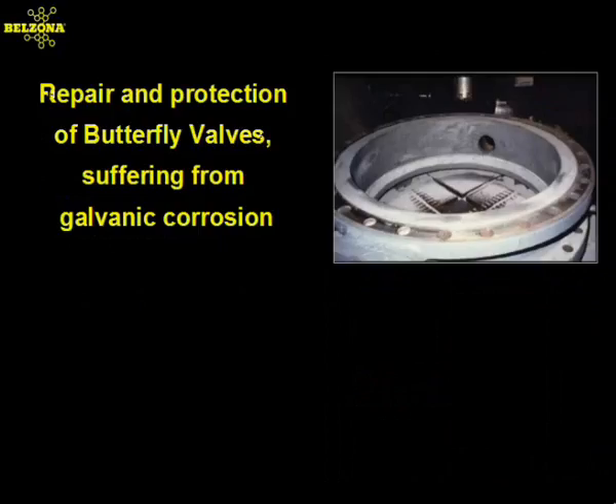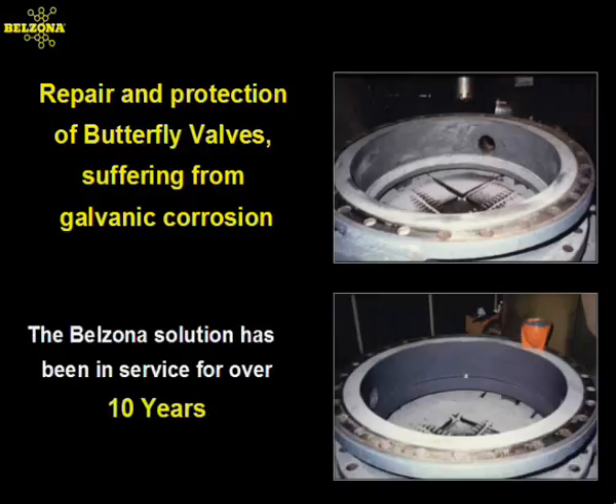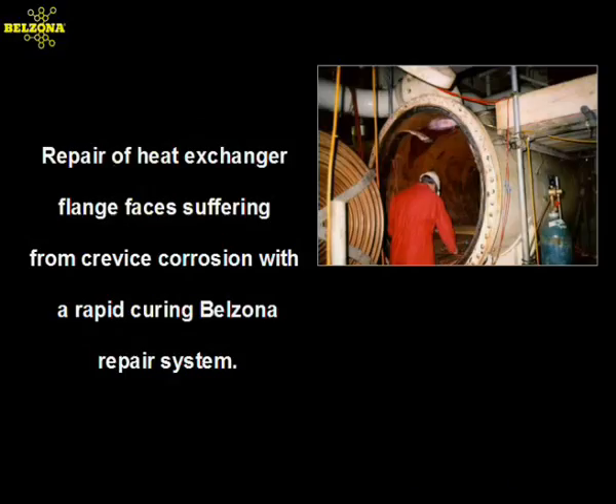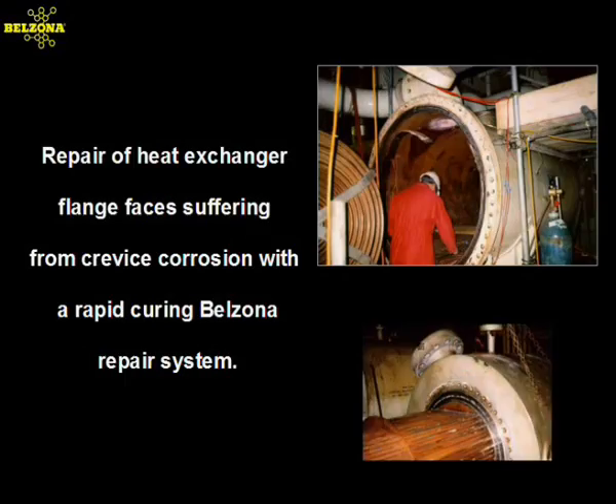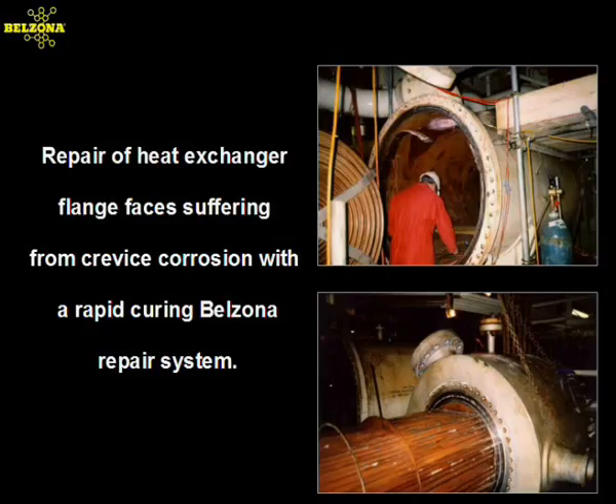Erosion corrosion in fluid flow environments is a severe problem which occurs in many forms. This butterfly valve body suffers from corrosion, accelerated by galvanic attack, and required a Belzona paste grade to repair the damage, followed by 2 coats of a special ceramic-filled coating system for long-term protection. Heat exchangers are another common problem area where the Belzona solution has been successful, whether it is to protect tube sheets suffering from bimetallic corrosion, or as in this case to repair the crevice-corroded flange face using an emergency grade to ensure a rapid turnaround.